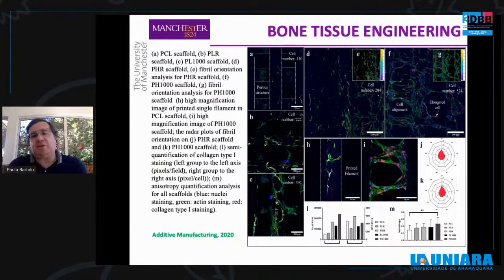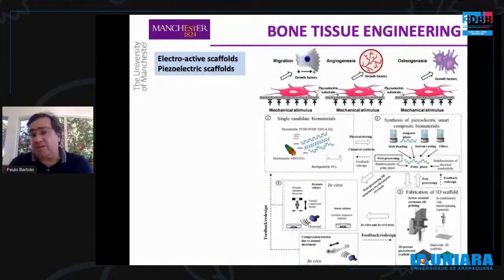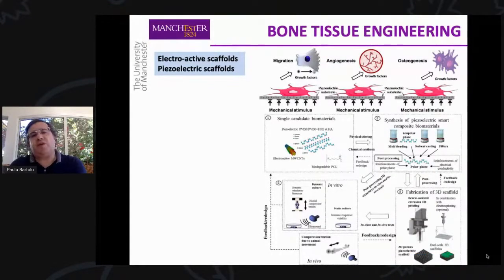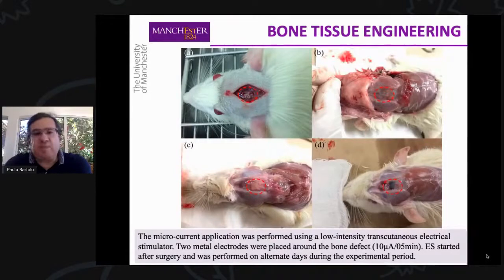We controlled the alignment of the fibers by increasing the rotational velocity in the electrospinning system, and by increasing the alignment of the fibers, we increased the cell anisotropy and obtained a more organized cytoskeleton. Bone, as you know, has piezoelectric properties and also reverse piezoelectric properties. So we are also focusing on the concepts of electroactive scaffolds and piezoelectric scaffolds to enhance both osteogenesis and angiogenesis. An example is the work that we are doing. This is also in partnership with colleagues in Brazil, colleagues in Araraquara.